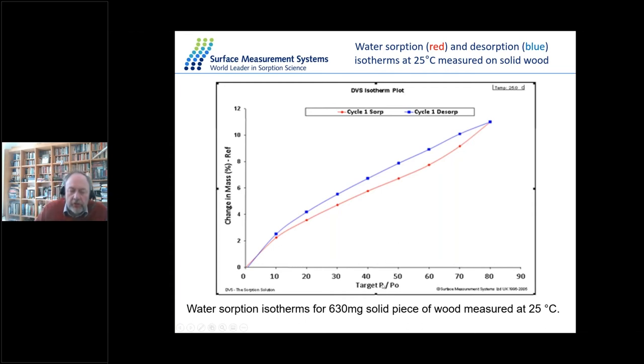So what you can see here on the x-axis is the P over P0, which is basically, in our case, the humidity. This is an experiment with water vapor done at 25 degrees on a solid piece of wood. So someone's cut a piece of sample just over about half a gram. We've run that experiment for a few days, and then we measure the isotherm points. And what you can see is this experiment went to 80% humidity, which is what the customer wanted. And at 80% humidity, we had just under about 11% moisture content. So in other words, the mass of the sample when it was dry increased by 11% by the time it went to 80% humidity. And then when I went to go down, it returns pretty well to zero.